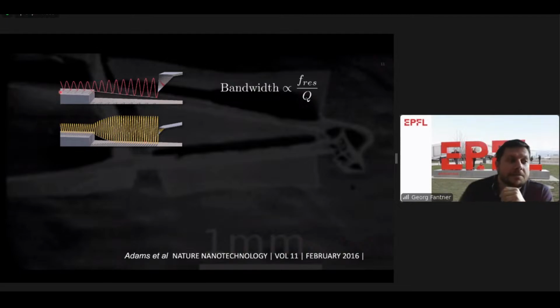We can characterize the speed with which we can actually detect the surface topography with a bandwidth. So how quick or what changes can we still detect as they're coming, at which frequency can we still detect them with the cantilever when it's oscillating. And this bandwidth is proportional to the resonance frequency, like I explained here. And it's also the Q factor, because the Q factor of the oscillator tells us how many cycles the cantilever has to oscillate in order to get to the new steady state. And this Q factor has to do with the amount of damping that is inside the cantilever.